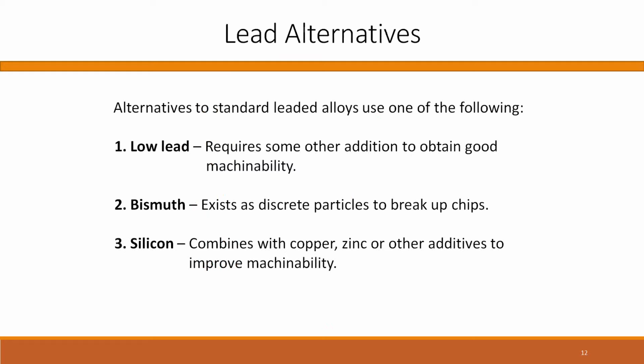Now that we're not allowed to use lead galore in our machining alloys because you're trying to make potable water parts, there are 3 different approaches right now that are being taken to get better machinability without lead. One is to have low lead to begin with, and then add something else. And those something elses can be shown in the periodic table, which I'm going to show you in a bit. It's something that's trying to make another phase in there that can break up the turnings. And I have some microstructures that will show you that in a bit.